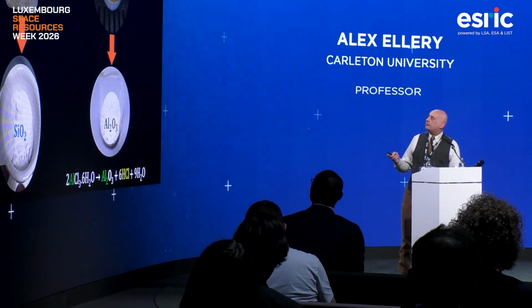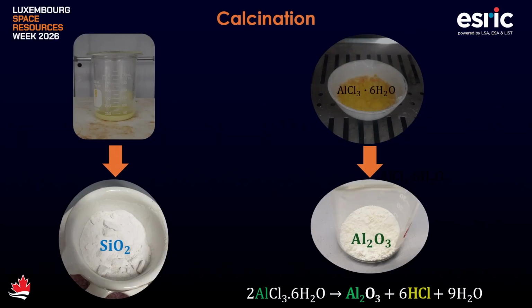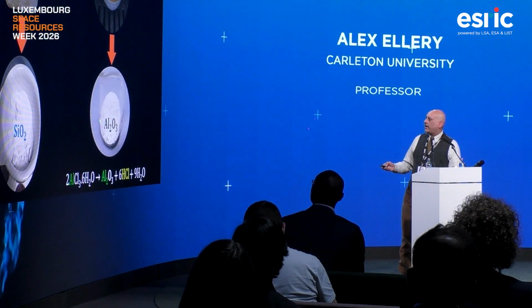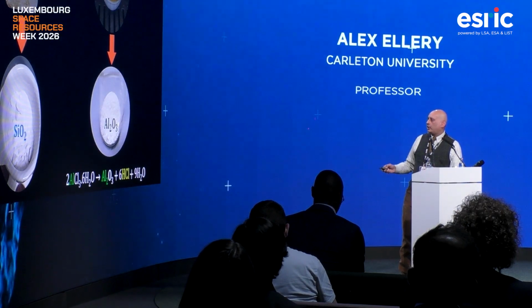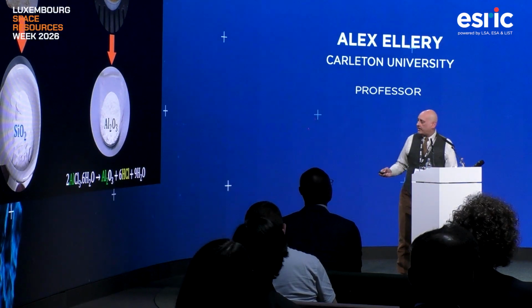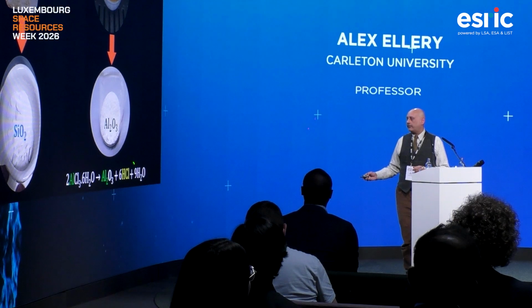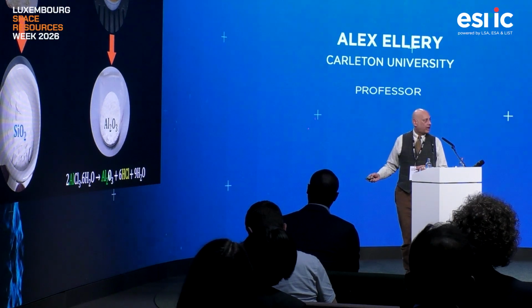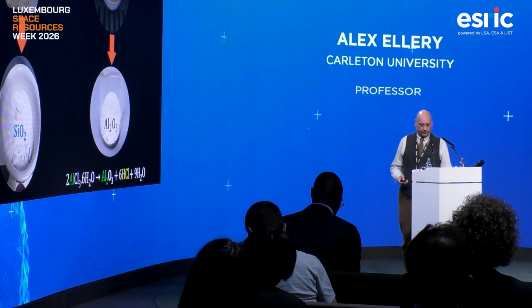So the next stage was to roast everything, calcination. And we dried the silica. We then discarded it because we didn't use it for anything. We could have turned it into glass or something like that, but we didn't actually do that. Again, we calcined it and ended up with alumina here. And in fact, we also recycled the majority of the hydrochloric acid that we used.